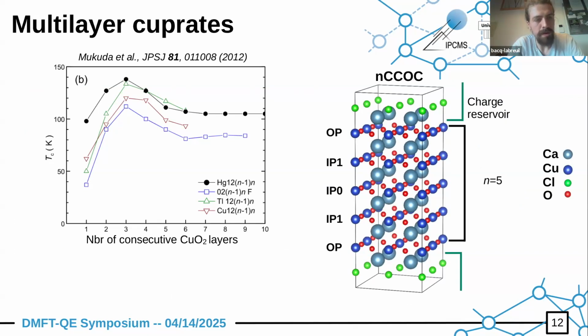So we got interested in multilayer cuprates. One reason is quite simple: there are materials which are quite complicated to describe with effective models, and for good reasons. So usually with cuprates, we think of them as having one copper-oxygen plane separated by charged reservoir layers. The difference with multilayer cuprates is that you can actually have n, so a certain number of copper-oxygen planes in consecutive, which are then separated by charged reservoir layers. And the superconducting properties of these compounds depend quite a lot on the number of consecutive copper-oxygen planes that are separated by these charged reservoir layers.